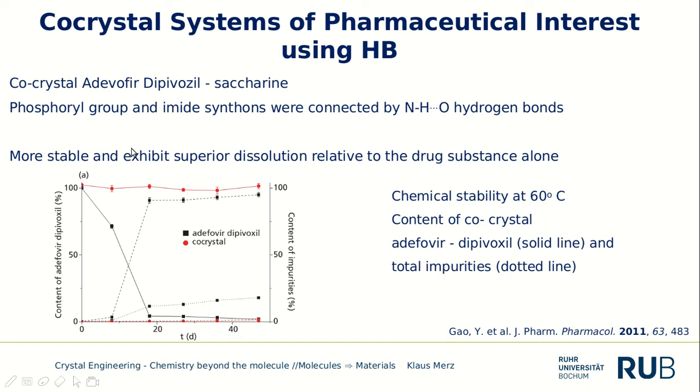We see very nicely that after a long time, 10, 20, 30, 40 days, 60 days, your co-crystal product is still stable. It works here at 100% and there is nearly no decomposition.